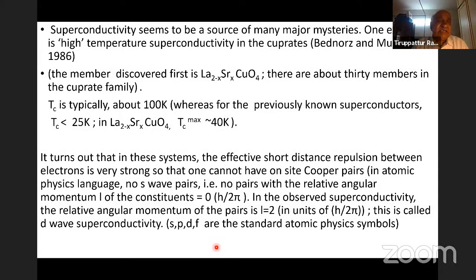If you have these Cooper pairs and you can describe the material as a collection of these Cooper pairs with all the same phase. The material which consists of such a collection of coherent Cooper pairs is a superconductor. Bardeen, Cooper, and Schrieffer identified the wave function used by Ginzburg and Landau as a certain amplitude of the thermodynamic average of the electron pair field. By doing this they were able to discover the atomic level origin of superconductivity of the pairs of the parameters assumed in the Ginzburg-Landau theory. Now, I mentioned this also for a selfish reason. The reason is that superconductivity seems to be a source of major mysteries.